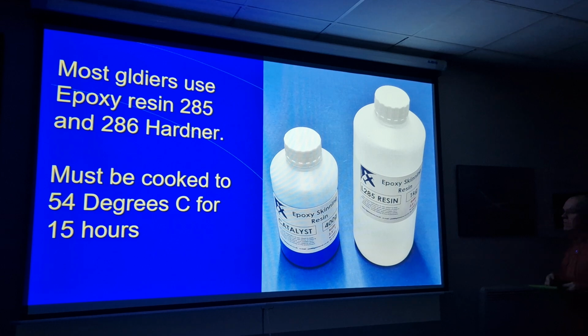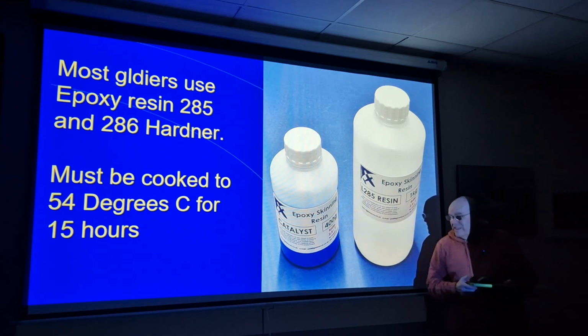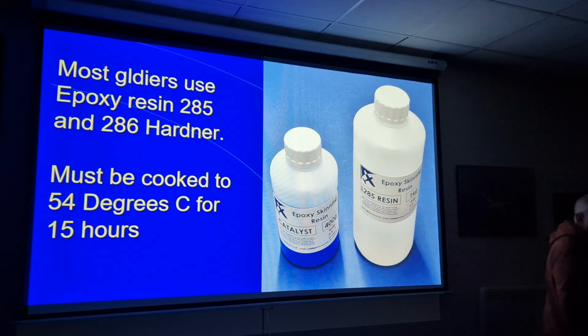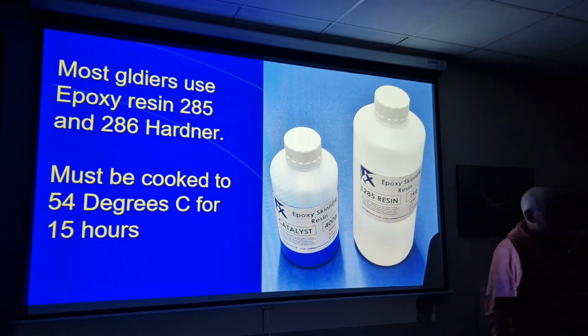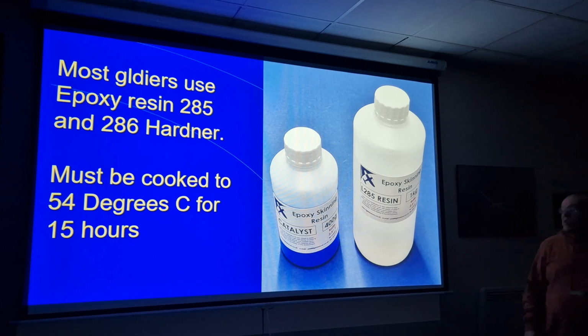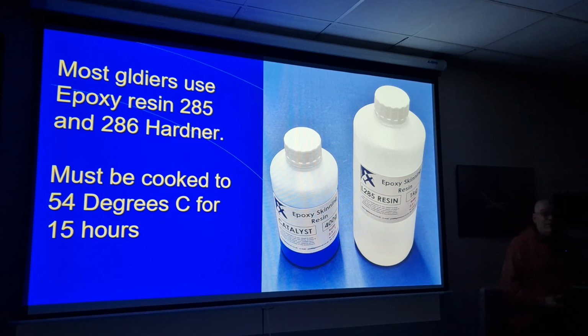So what do we build gliders with? We build them with, in this case, epoxy resins. Now, there are a few different types, and most of the older gliders, built until about the year 2000-ish, were built with an old obsolete resin called 162-113. And what that means is if you break a main spar, say on an old K1, the manufacturers will not let you repair it because you can't buy the same resin it's built with. Because the theory goes that these might have slightly different expansion coefficients. So hence we can't do spar repairs to old gliders. All the manufacturers agree on this principle.